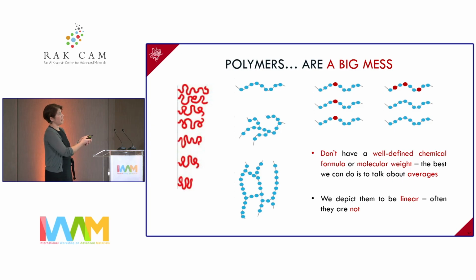And then finally, even thinking about defects, I'm showing you two cases here. In both cases, there are 3 defects amongst the 3 chains. In this case, 1 per chain. Here, 3 on one chain and none on the other. But using characterization, we cannot tell apart the difference between these 2 samples. All we can really do is always talk about averages of molecular weights or chemical structures, and that makes it a bit harder to do really careful structure property relationship studies for polymers.